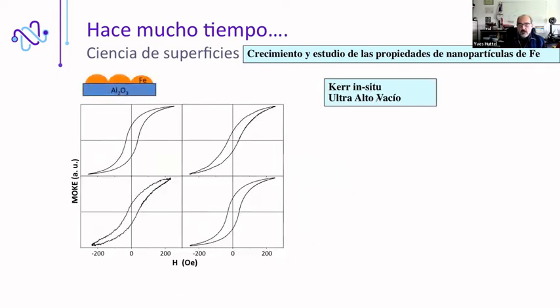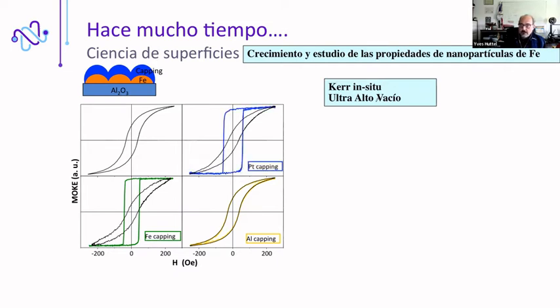What we did is to study the magnetic properties of these clusters using a Kerr effect. And here you have the hysteresis curves of different deposits of these iron nanoparticles. And what we did in situ was to deposit a capping layer on top of these nanoparticles. We started first with aluminum, and as you can see, the hysteresis curve is not modified. We have not modified the magnetic properties of the system. But this is not the case when we deposit iron capping or platinum capping or even palladium capping.